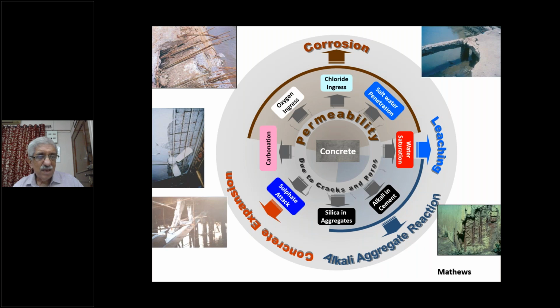Alkali aggregate reaction is very rare in our country, but very important. In the UK, there is an area which gives a lot of alkali aggregate reaction. So we are lucky. This happens because the alkali in the aggregates comes in touch with cement and produces a material called alkali-silica gel, an expansive material. It expands and cracks the concrete. But here too, the alkali aggregate reaction only takes place where there is water or a high level of moisture in the atmosphere.